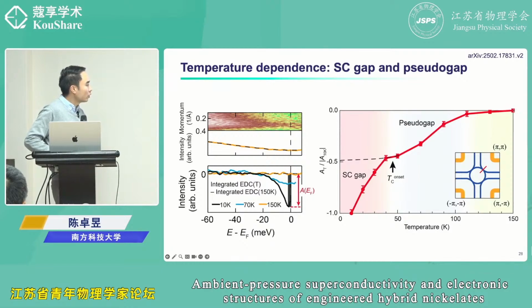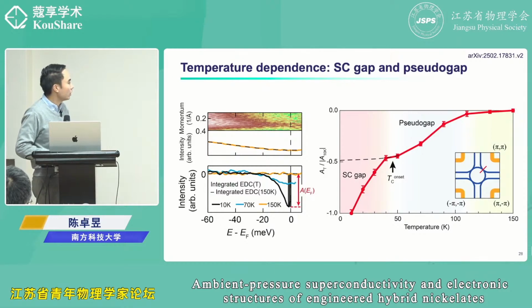So from 150 Kelvin, when we decrease the temperature, you first see a gap without a coherence peak, and then under the Tc onset, you see another, very quickly dropping gap happening, also with the coherence peak. Combining the existence of the coherence peak, the backbending behavior, and this temperature dependence corresponding to the Tc, we can say that this should be a superconducting gap.